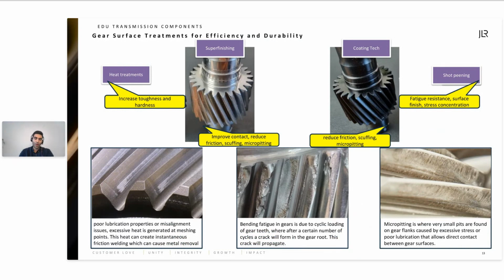Super finishing, although expensive, is an important surface treatment for us to reduce the contact, reduce friction, and of course, thermal dissipation at the interfaces, therefore reducing scuffing and micropitting. Again, although costly, coating technologies could help with reducing friction and increasing the scuffing and micropitting performance of the gears. And of course, shot peening being something that the gear industry has been doing for quite a few years.